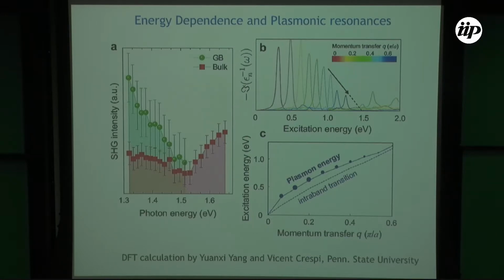One question that can arise is how this momentum transfer occurs. In the TEM image that I have shown, and if you look at the second harmonic, you think that the grain boundary is a straight line. So you wouldn't expect that the light couples with this and generates plasmon resonance, but in fact the grain boundaries are not very long. They are a few nanometers long, then you have a break and another grain boundary rotated with respect to each other.